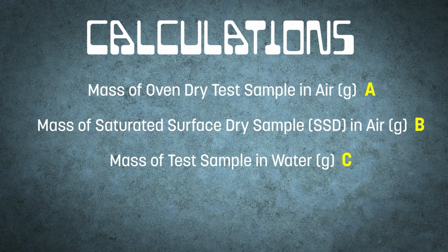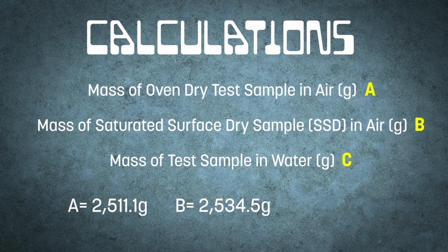For this example, the weight of the oven-dried specimen is 2,511.1 grams, while the weight of our SSD sample in air is 2,534.5 grams, and the weight of our submerged sample is 1,535.6 grams.